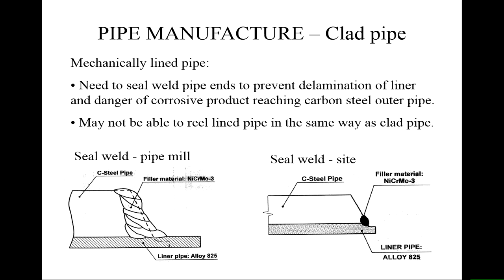So with these mechanically lined pipe systems, they don't reel very well. You could imagine that as you bend the pipe, it's easy to buckle the inner liner away from the main part of the system. So you bend the pipe and the inner liner collapses and buckles away, and you get large void spaces at the interface, which can be problematic for gas entrapment and for corrosion. That generally means you have to have larger radii of curvature when you reel them up to avoid that from happening. So it's not impossible to reel these systems, it's just difficult.